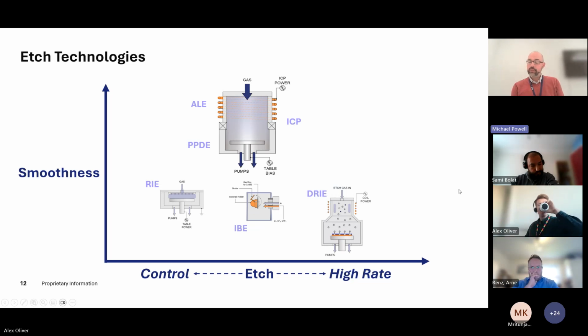And on the etch side, again, it's control versus rate. So what we have here are a variety of technologies that allow us to control how high your selectivity is for what you are etching away. And then on the other side, it's rate, and we've also got smoothness. So when you're doing a plasma technique, you'll often find that what you get at the end is a rough surface. Now, if you want more smoothness, you can go over to atomic layer etch rather than a standard etch. And then on the other side, it's the rates and it's the selectivity. And these various technologies allow you to play between smoothness, control, and rate. Next slide, please.